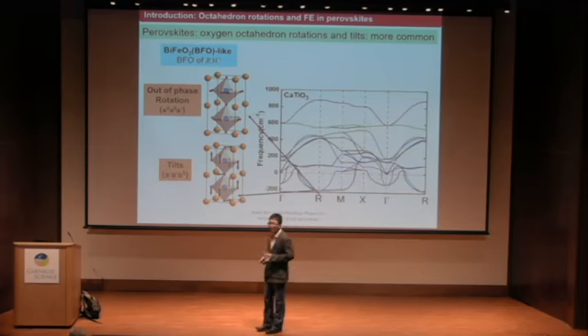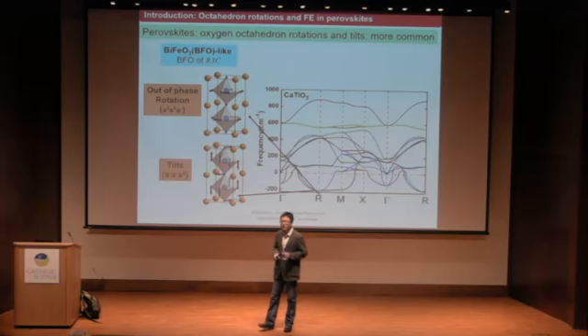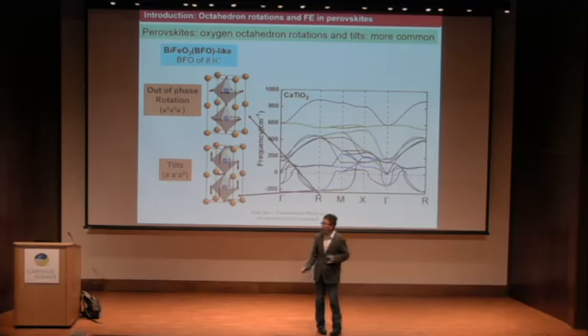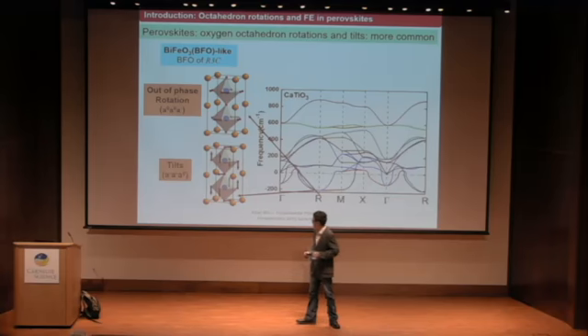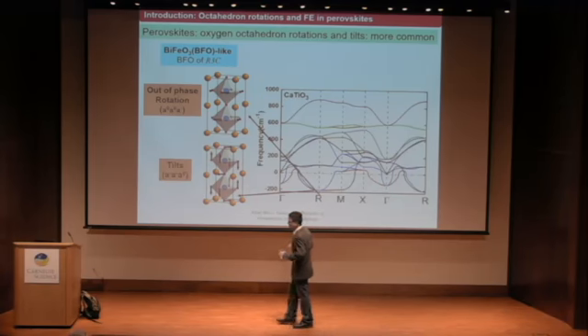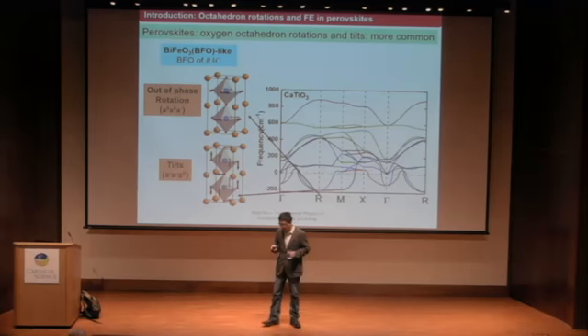For example, if both octahedral rotations originate from the R point, as in the bismuth ferrite phase R3c, we can understand this structure by an out-of-phase rotation around the 001 direction and tilting. Tilting is the same - they both originate from R point instabilities.